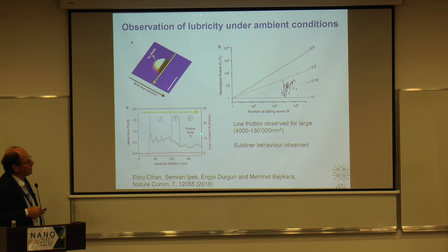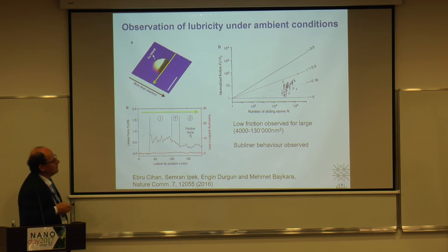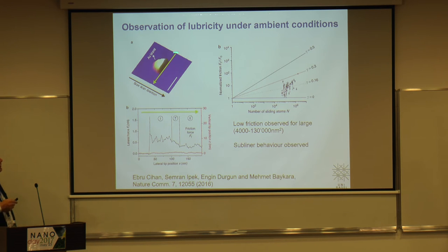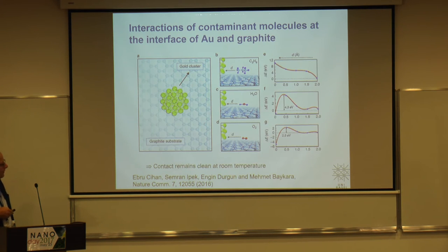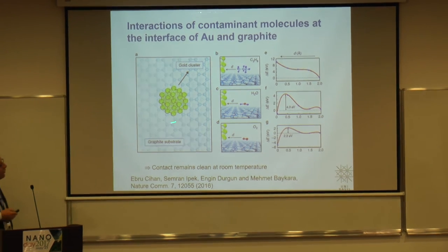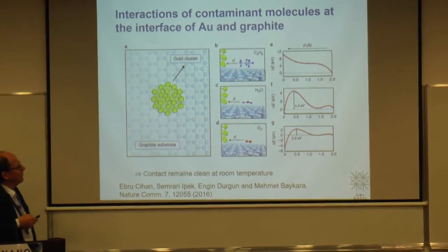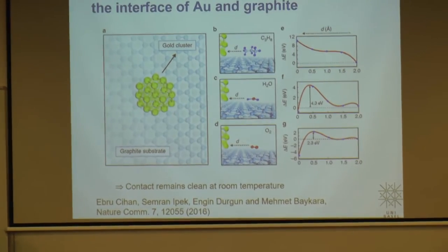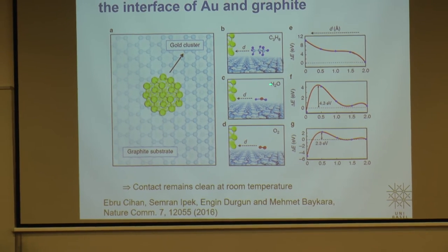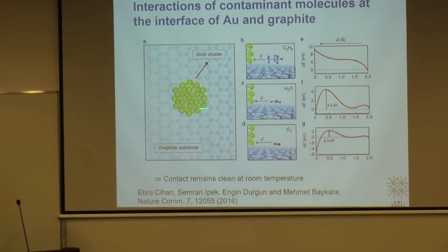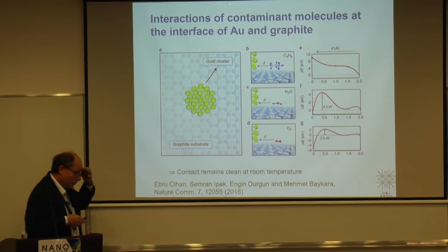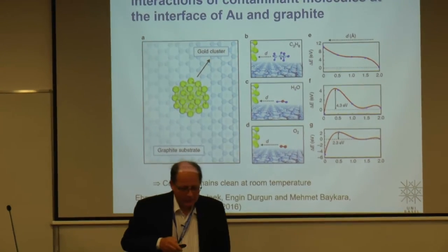And still the forces are very small. So it seems to be possible that the interface here is clean. I think they showed here from Engin Durgun that the idea is that the molecules, what we would call dirt, is either some alkanes or water or whatever. They cannot easily enter this interface, and that's probably the reason why it stays clean under this condition.